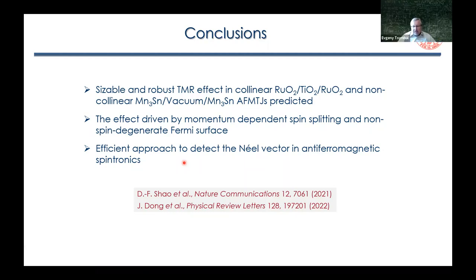Yeah, in principle, in a simple picture, you can argue that you have tunneling from left to right, and you have a certain density of states at the Fermi energy, and this provides you a certain number of electrons which tunnel from the left to the right. So in ferromagnets, you may argue that based on this density of states, you already can have a tunneling magnetoresistance effect, because this density of states will be different for up and down spin electrons. In antiferromagnets, you cannot use this argument, because if you integrate over all these momenta, you will find the same result. So you need to have some selectivity in the wave vector.